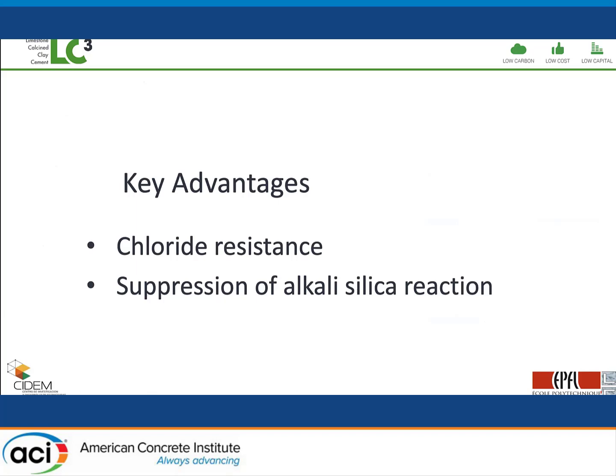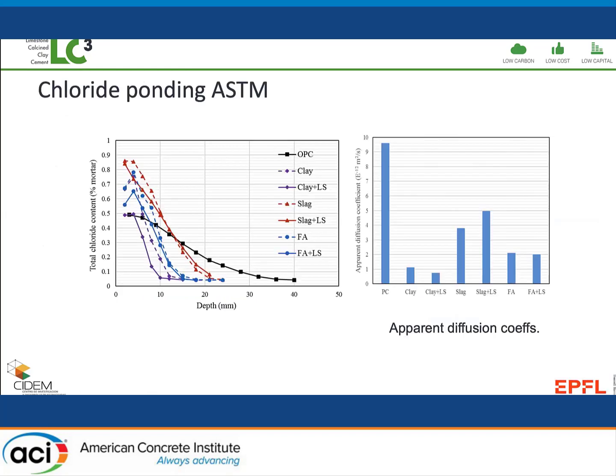So the key advantages we found are chloride resistance. This was already talked about this morning, and alkali-silica reaction. This shows the results of those different mixtures in terms of chloride ingress. So, this is the OPC with very big penetration.